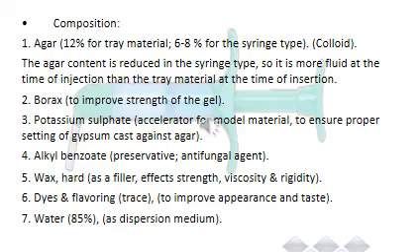2. Borax, to improve the strength of the gel. 3. Potassium sulfate, an accelerator for the model material to ensure proper setting of the gypsum cast against agar. 4. Alkyl benzoate, a preservative and antifungal agent. 5. Wax, hard, as a filler, affects strength, viscosity and rigidity. 6. Dyes and flavoring traces to improve appearance and taste. 7. Water, 85%, as dispersion medium.